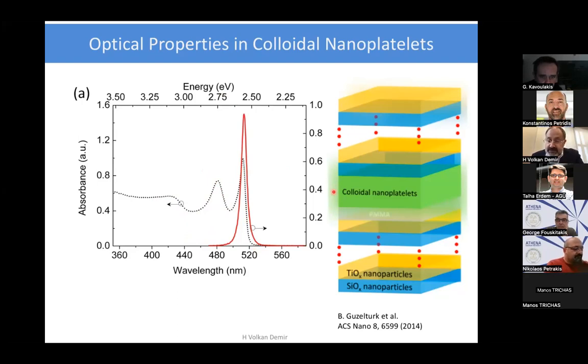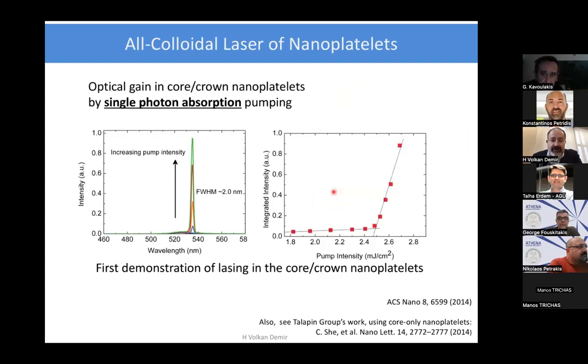And this is the structure we utilize to see their gain properties with their absorption cross-section being high, both for linear and nonlinear regimes, and having their local density of states to be large enough because of the very tight confinement, we expected to observe high gain out of these materials. And that was the goal, where we pushed this nanoplatelet film to go into gain. And using single photon based absorption, we were able to see successful gain behavior with the expected line width shortening, narrowing, and also expected integrated intensity versus fluence behavior. Now, this was from core crown nanoplatelets as the first observation of gain from these quasi two-dimensional structures.